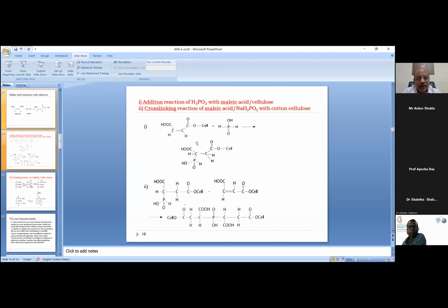Now, one more extra reaction that is possible is if you use, say, a phosphorus-based compound, then that can further react with this. And as you see here, it is a simple addition reaction. Nothing is eliminated, nothing is substituted, and it is a simple addition reaction, resulting in retention of phosphorus in the total entity. Once it further reacts, you find that it is now a much larger unit with phosphorus embedded. So the advantage is if you have phosphorus, then there is possibility of fire retardancy. So this way we can have multiple functionality on the fabric by using this as a catalyst. So this will catalyze the cross-linking, and at the same time, this will also help to a certain extent in increasing the flame retardancy.